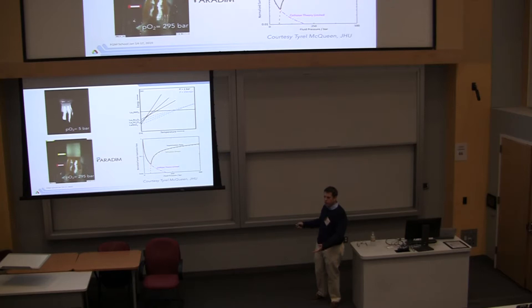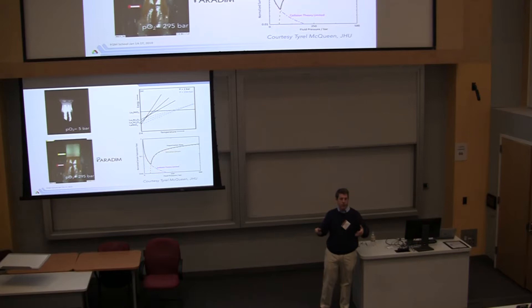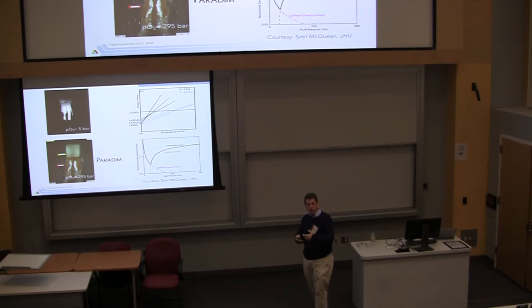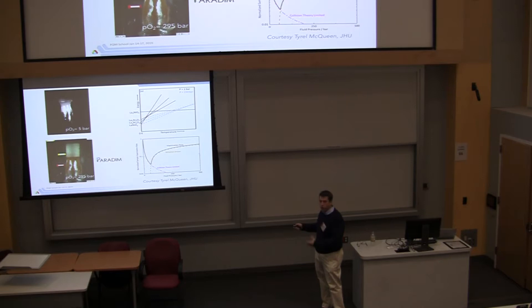Well, here's another example here. If you go to higher pressures of oxygen, because this is a gas, you're going to shift the reaction to the left and make the oxide, make the compound that you want, rather than some low oxidation metal plus oxygen. Here's a real life example of it. Here's copper oxide, plotted here as a function of oxygen pressure over many decades, and temperature up to 1200 degrees.